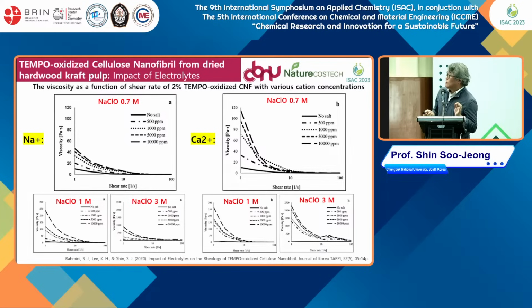We tried to make TEMPO-oxidized cellulose nanofibrils with different amounts of oxidant. We usually use NaClO, sodium hypochlorite, and different levels of oxidation give us different amounts of carboxylate. Low charge oxidant and high charge oxidant have different gel strengths. With calcium cation, we can see the decrease of gel strength after the optimum condition.